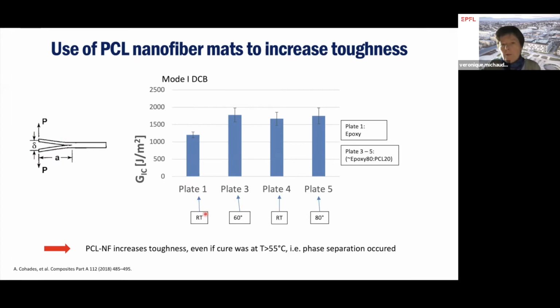of the material. We had a plate that was an epoxy plate that was our reference material with the G1C around 1 kilojoule, a bit over a kilojoule per meter square. Then we did a plate which was cured at room temperature only, one that was cured at 60 degrees, so above the melting point of the PCL, and one that was cured at 80 degrees, so way above the melting point of PCL. What was interesting is that in all the 3 cases, the toughness of the material was quite improved. Whether we actually preserved the nanofiber mat structure below, so it was not molten and it remained, or actually even a bit better above the nanofiber mat melting.